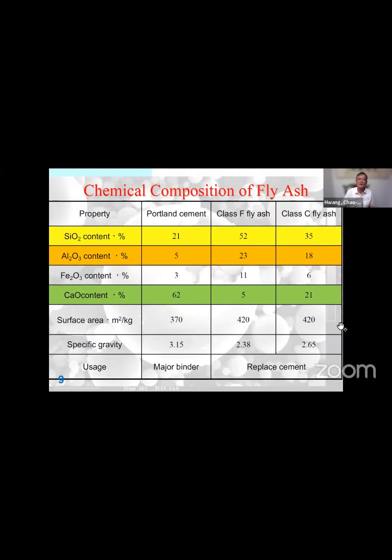By looking at the chemical composition of fly ash compared with Portland cement, class F fly ash contains less CaO, or calcium oxide, and class C fly ash contains large CaO. So class C is more reactive, but a little bit harmful to durability. As compared with cement, it's about 62% calcium oxide.